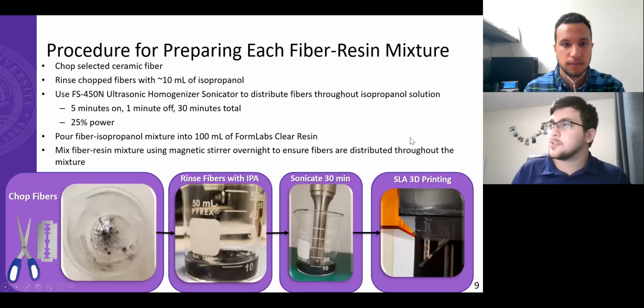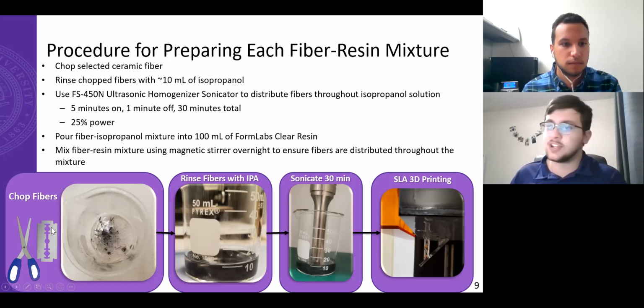So the procedure for each of our fiber resin mixtures involved chopping each of the selected ceramic fibers. This was initially done with a pair of scissors and just dropping the fibers into a beaker, kind of shown here. There were not necessarily consistent lengths, which will come up in the consistency check at the end of the presentation, or any of the PowerPoints.